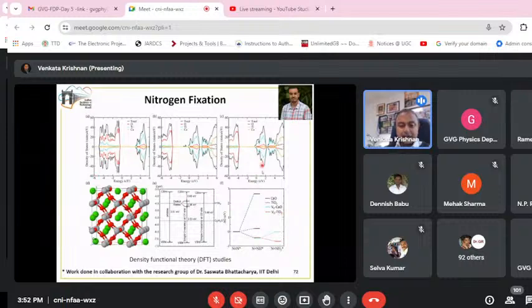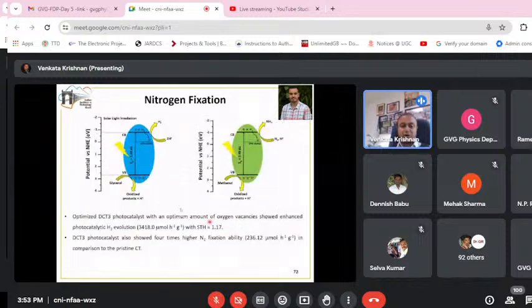Then we did some theoretical calculations in collaboration with the group of Dr. Saswata Bhattacharya. These are density functional theory calculations which support the experimental results. Based on all this, we deciphered a mechanism for hydrogen evolution, and subsequently another mechanism for ammonia fixation. We got an STH efficiency of 1.17, and the nitrogen fixation to ammonia was 4 times higher in the defect-rich samples compared to the pristine samples.